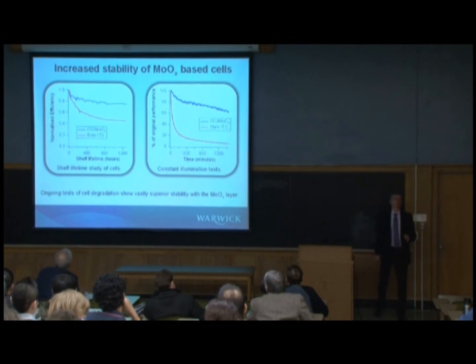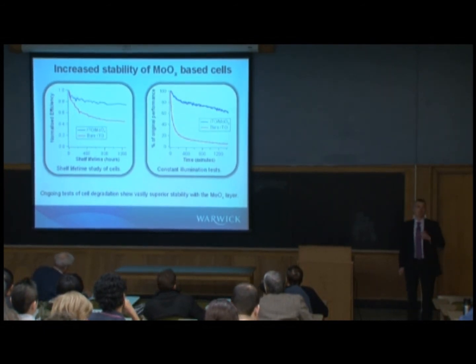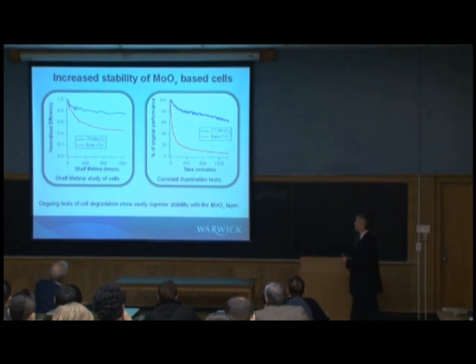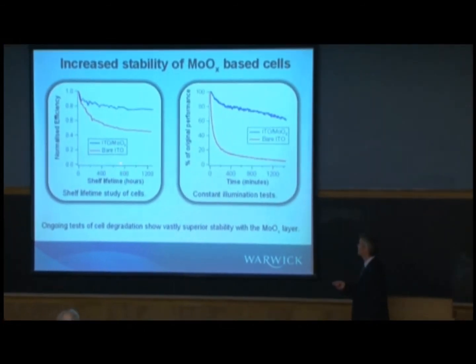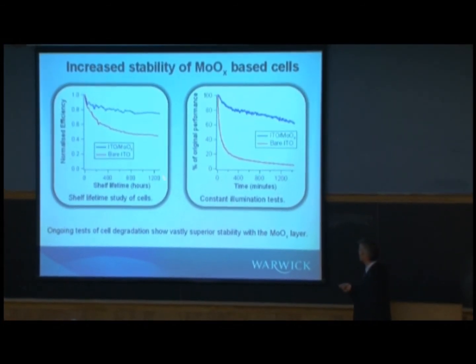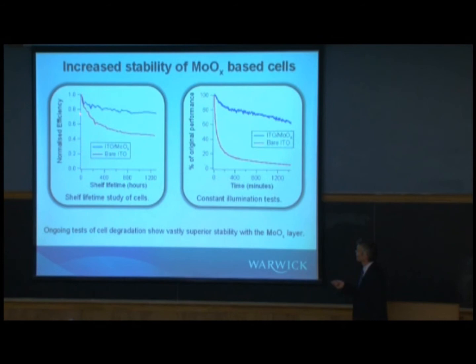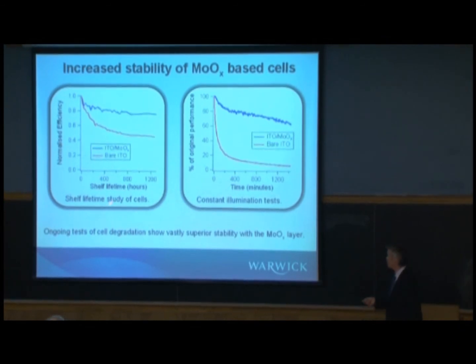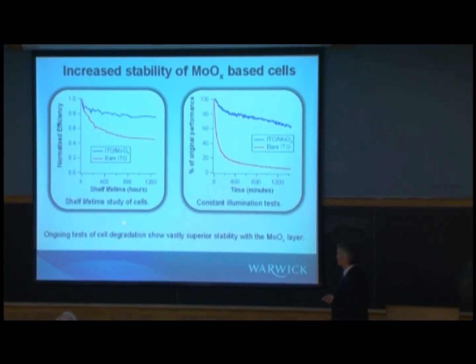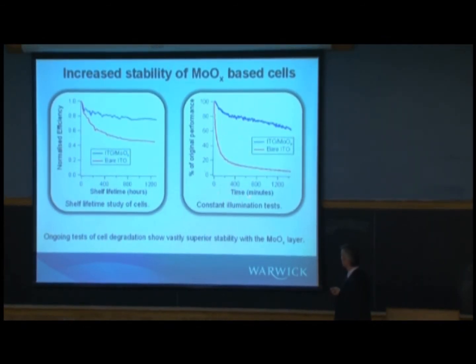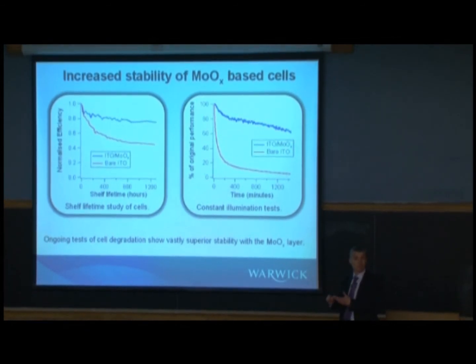What they will lead to is improved stability, irrespective of the organic materials you use. And this just shows, I can't remember which devices they are, which materials, but it just shows normalized efficiency of a device with and without the molybdenum oxide over a long shelf lifetime of hundreds of hours, and also under constant illumination in our solar simulator.